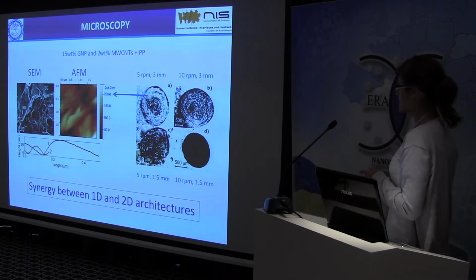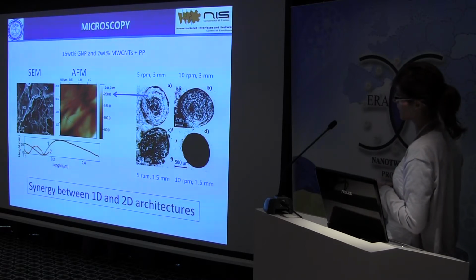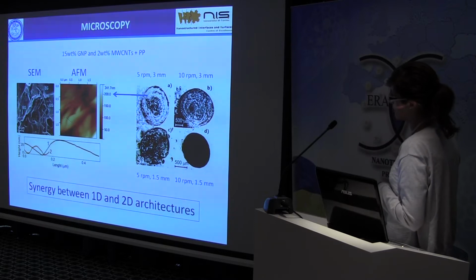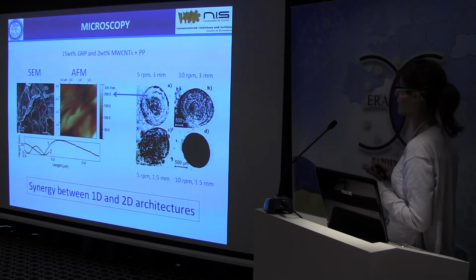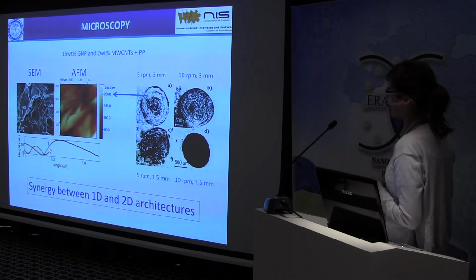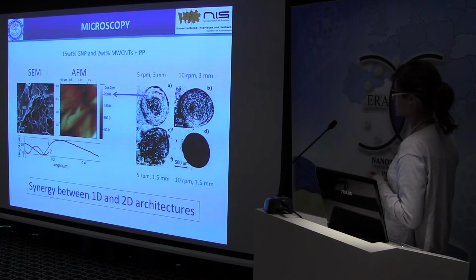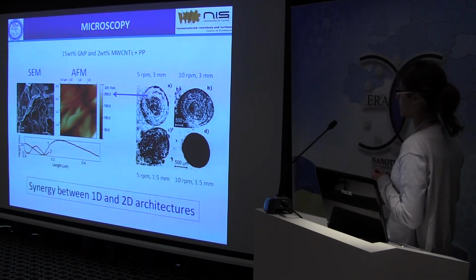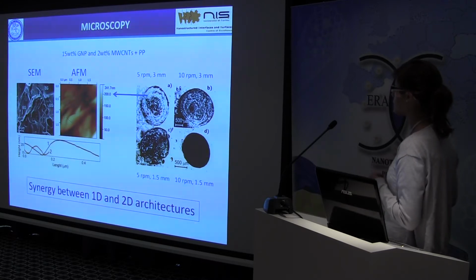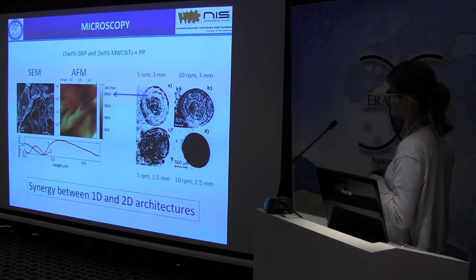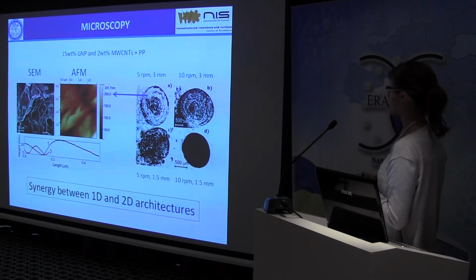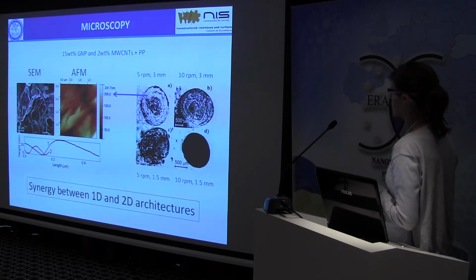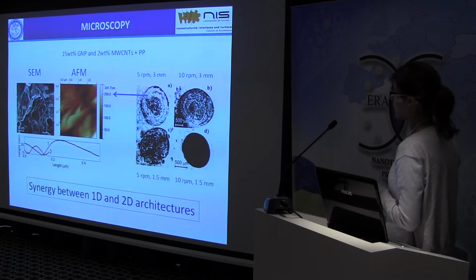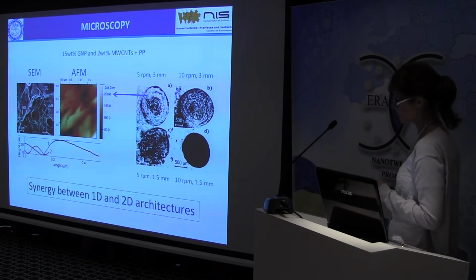In these areas there is the presence of both multi-walled carbon nanotubes and graphite nanoplatelets. In the SEM image, the multi-walled carbon nanotubes are highlighted by dotted lines, and we can see that they can help the formation of the conductive network, bridging the adjacent graphite nanoplatelets. And so we can say that in these composites there is a synergy between multi-walled carbon nanotubes and graphite nanoplatelets in enhancing the conductivity of these composites.